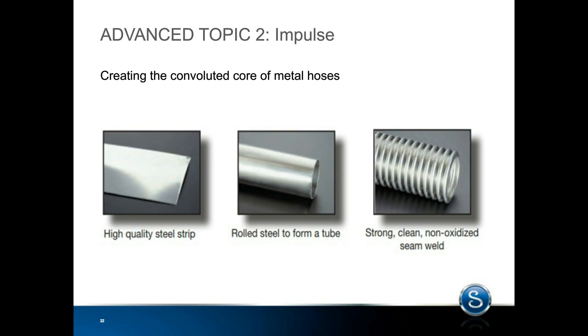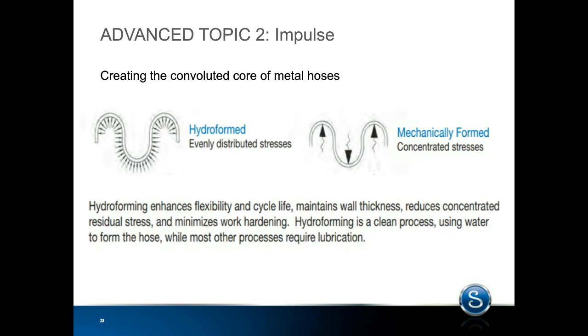And those convolutions can be formed two different ways. They can be formed mechanically, which essentially is a press form that pushes the material into the convolutions, or they can be hydroformed. And a hydroform is pressurizing the inside of that tube with water and making it create that form against a die. And that's a far superior way to form a metal tube because it spreads out the forces evenly along the entire core tube. And this keeps the core tube thickness the same, so we can maintain a 4-to-1 burst.